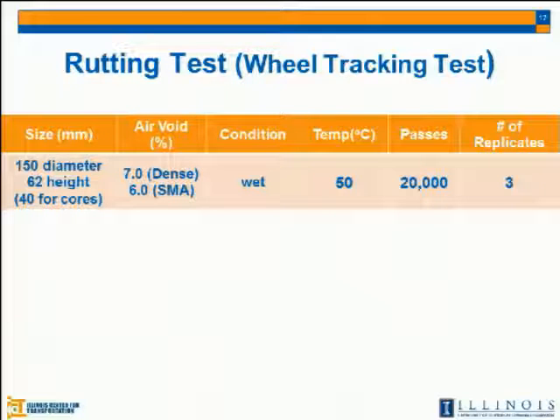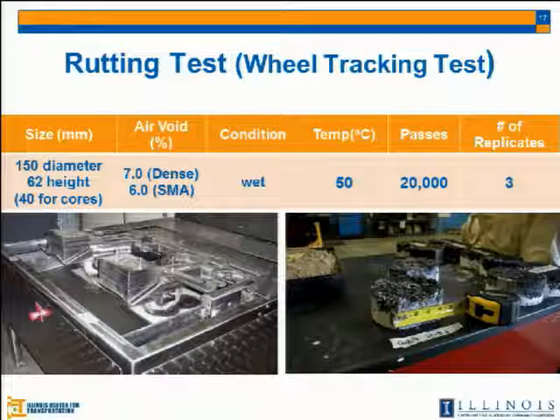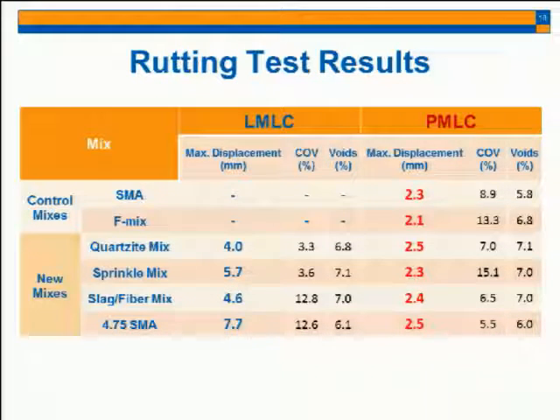Next is the rutting test. Using the Hamburg wheel tracking tester, we made a specimen and then did the test at 50 degrees C in the water bath, and then applied 20,000 passes, and then measured the maximum displacement of the surface. The lab prepared the specimen. The 4.75 SMA provided higher rut depth because of 7.3% asphalt content compared to the others with around 6% asphalt content. But for the plant mixed and lab compacted mix, we have almost identical rut depth after 20,000 passes of the steel wheel for all of the mixtures.